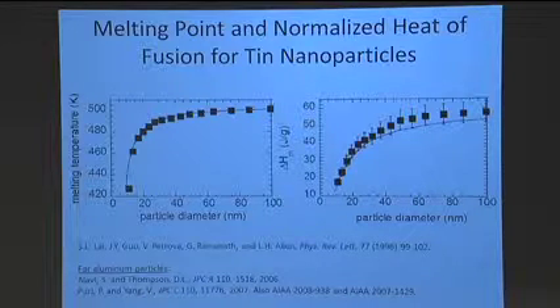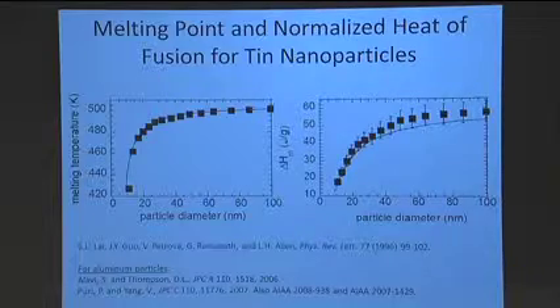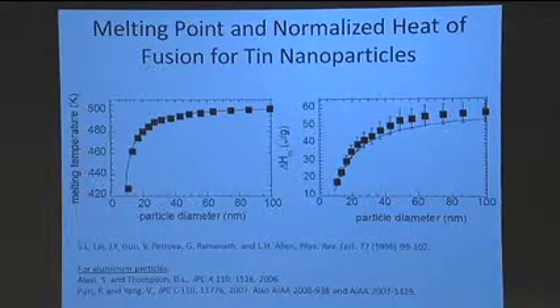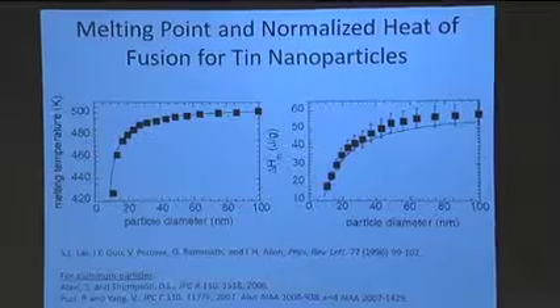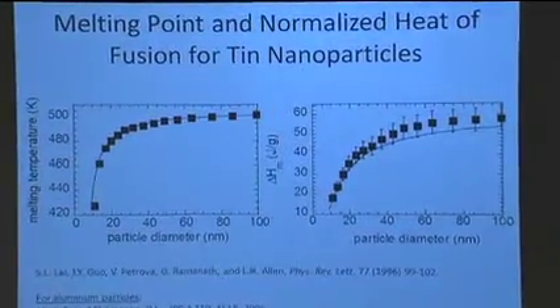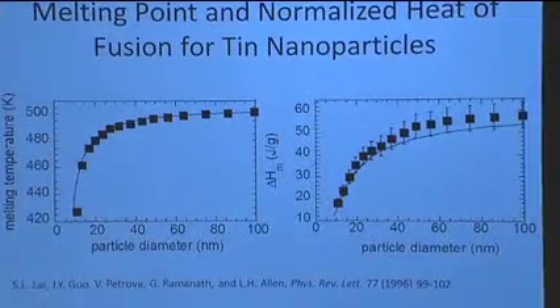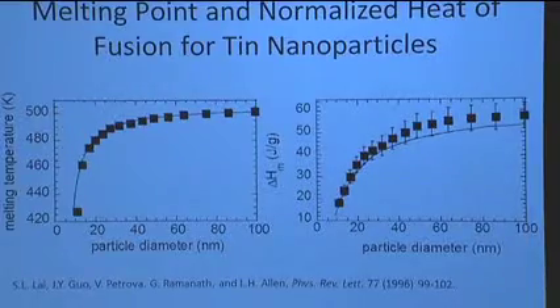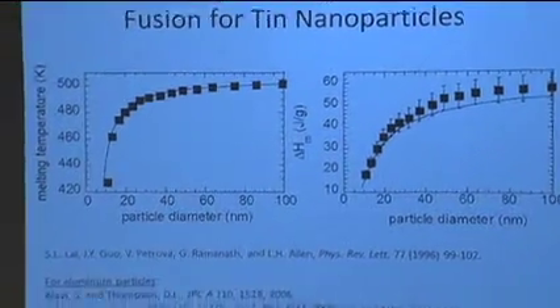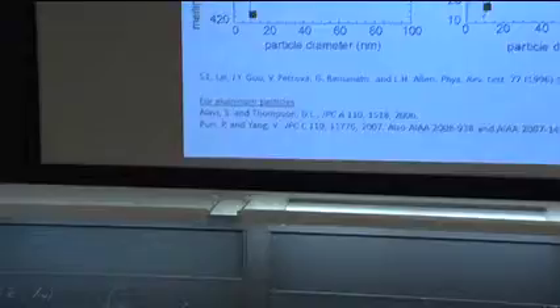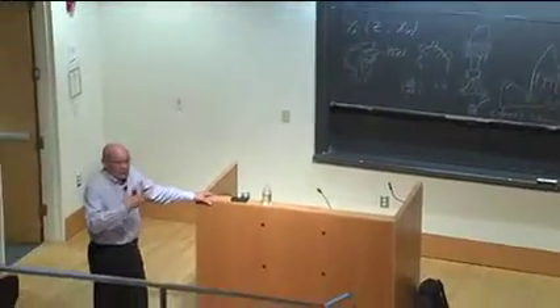What I'll show you in a little bit is how those physical properties end up being very important in regards to how, say, aluminum might burn. So if I can change the melting temperature of the oxide from 2,300 Kelvin down to 1,300 Kelvin, I'm going to have different ignition characteristics and a whole host of characteristics to deal with. In many respects, the reason these features show up is just because of the excess energy in the surface atoms and how that energy is being manipulated.